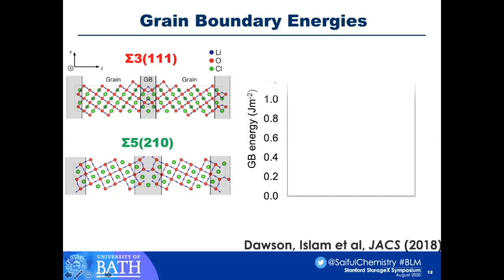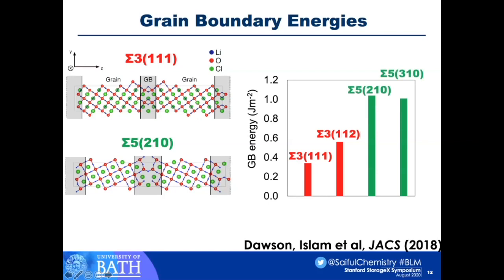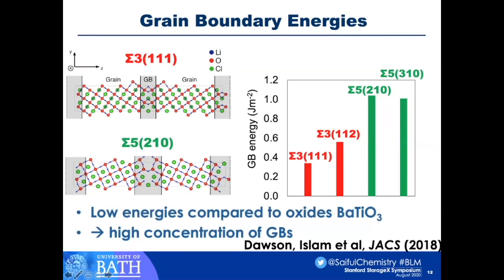We can calculate the grain boundary energies, and I'm summarizing them as simple plots. We find that the sigma 3 have relatively low energies. In fact, they're lower energies than the equivalent sigma 3 in barium titanate, again suggesting quite a considerable population of sigma 3 type grain boundaries. The sigma 5 are much higher energy, suggesting that they're less common or less concentrated within this anti-perovskite. So the general conclusion here is that the low energies compared to the oxide suggest a high concentration of grain boundaries within this anti-perovskite structure.